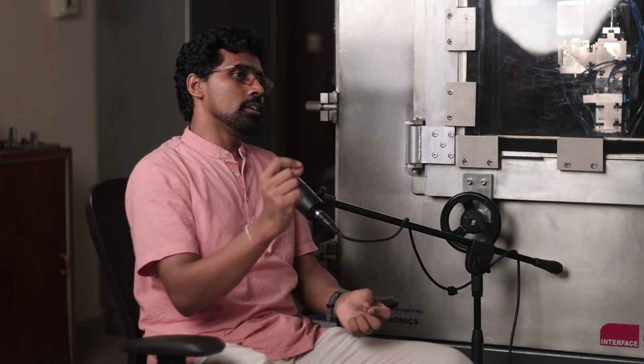First thing, I would want to know what your geometry is. So we would have to generate the CAD model of the logo that you have, how thick, the size, etc., all of that taken into account. Then once we have that model, we put it through slicing software, and then convert it into G code, M code. Those are the set of instructions given to the CNC, the laser, and the powder feeder, to control what laser power we should give, in what direction, at what speed the CNC bed should move, and what the powder flow rate should be. For each layer, no? Yes, for each layer.